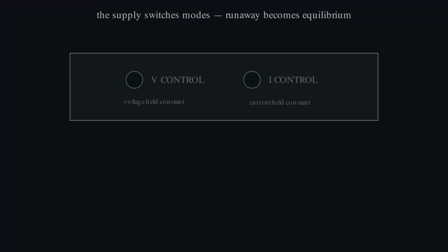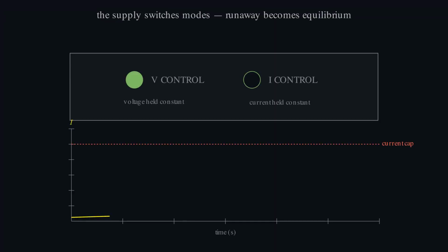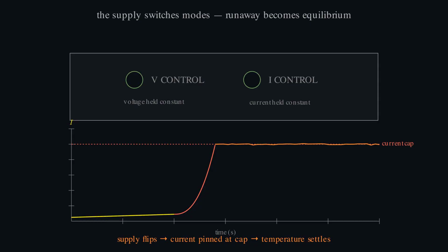When the current spike hits a preset ceiling, a few amps per square centimeter, the supply flips. Runaway becomes equilibrium. The temperature settles around 2000 Kelvin. The current sits at its cap. The voltage relaxes. And in those few seconds at 2000 Kelvin, the sample sinters. This is the trick. Flash sintering is a controlled bomb. You start a runaway. You catch it at the peak. You use the energy of the peak to do the work.